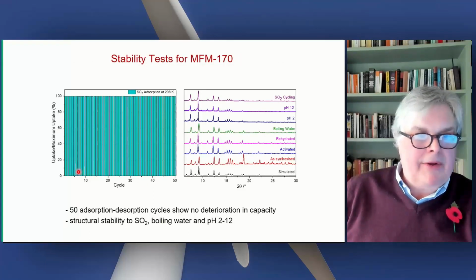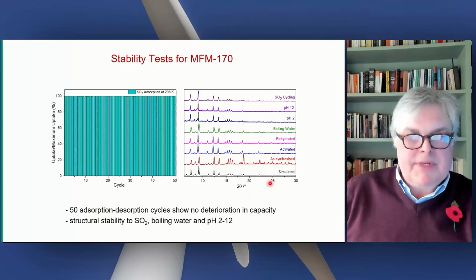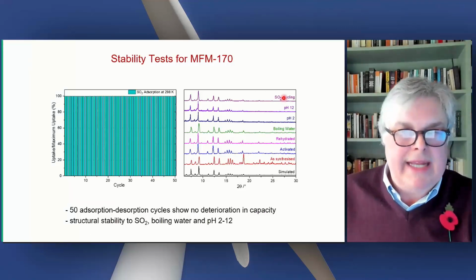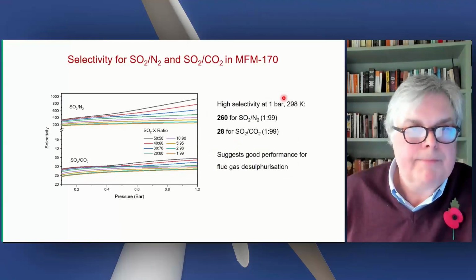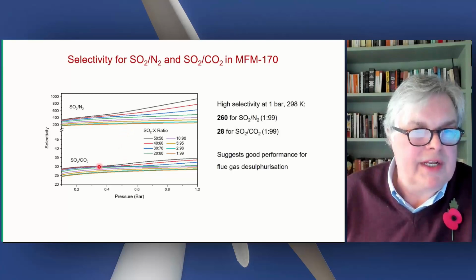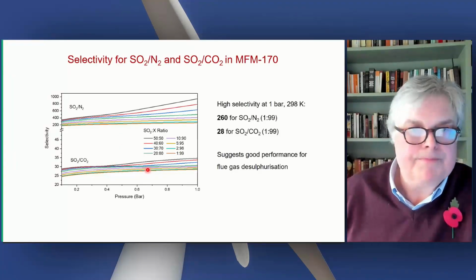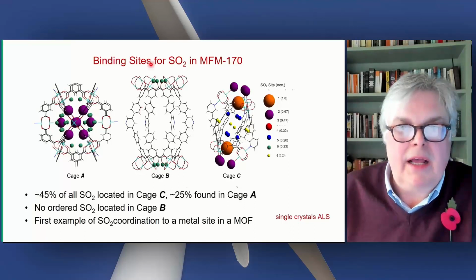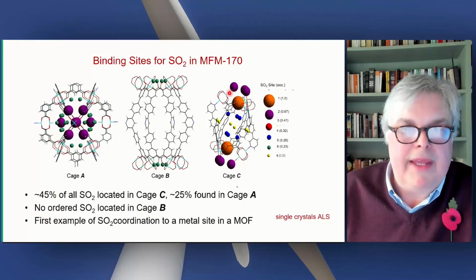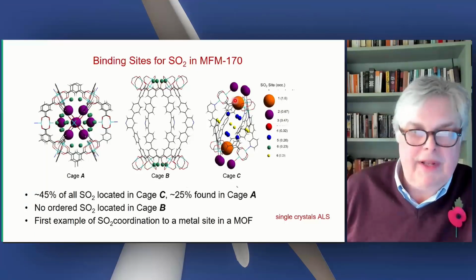And we can cycle this compound now 50 times. Here is the plot. The uptake of SO2 does not change. And with this material, here are the PXRD patterns. We can treat this in boiling water, pH 2, pH 12. On SO2 cycling, it does not show any deterioration by powder X-ray diffraction. The selectivity is good both for dinitrogen, and here is good selectivity against SO2. And we know where the binding sites are. This gives you a sense of the occupancy of the SO2 sites, not simply interacting with the open metal copper site, but also within the pores and interacting with the CH groups of the ligand.